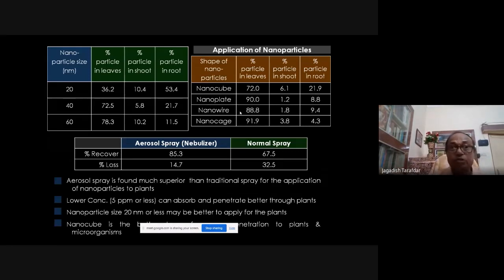But the best way of applying nanoparticle, we found, is the foliar spray. And when you go for foliar spray, you use as fine a nozzle as possible. If you have an aerosol sprayer, that is the best. Nebulizer, if you have. Why did we find this? When you are using a very fine sprayer, that is a nebulizer, environmental loss is only 15%, and we could recover almost 85% of the nanoparticle. But 15% could not be recovered, environmental loss. But with a normal sprayer, which we are applying now in the field, 33% loss is there in the environment.